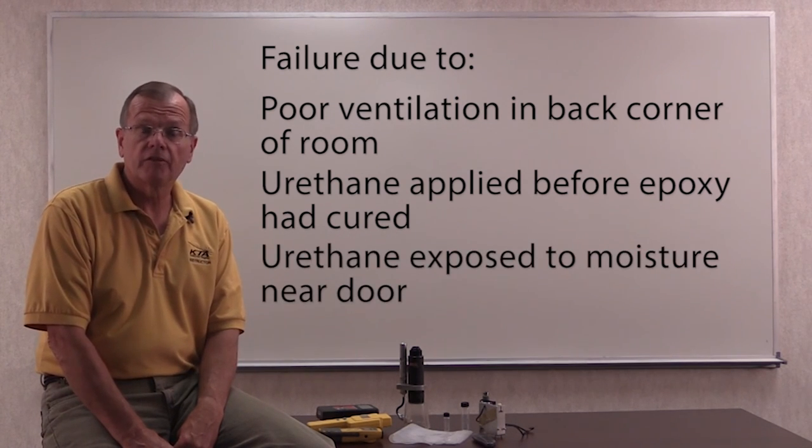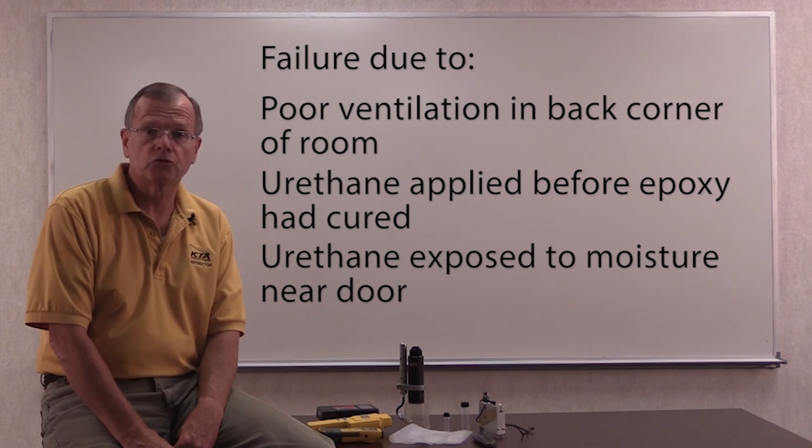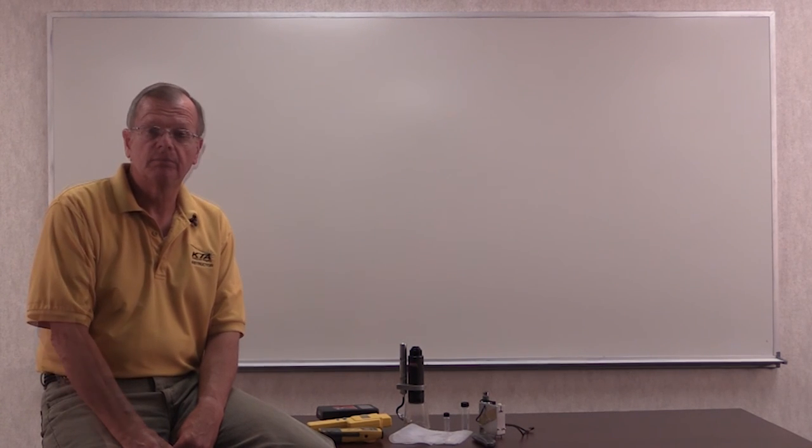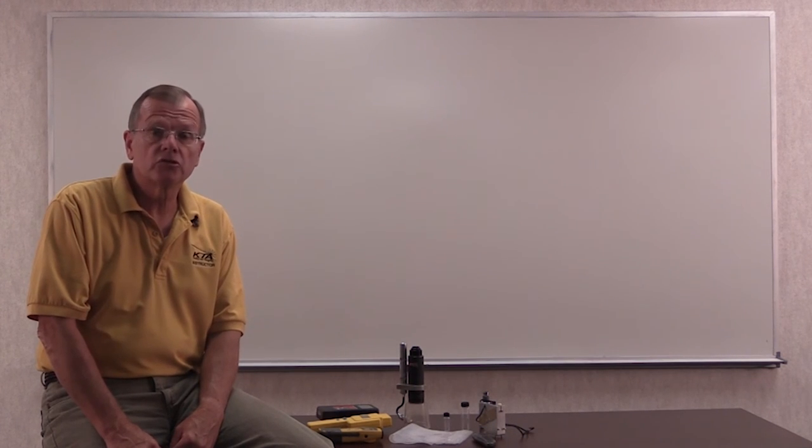And second, the failure near the door was due to the exposure of the clear urethane coats to moisture when applying the coating while the doors were open and it was raining outside. That's it for part six, which is the conclusion of this series.